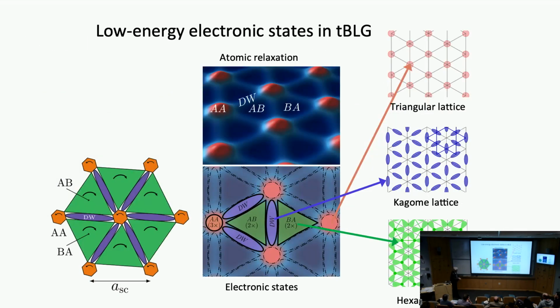And if you analyze this relaxation pattern that I showed you, it consists of three different lattices. These little sites here, the AA sites, form a triangular lattice. That's the triangular lattice. The domain walls form a Kagome lattice, and the AB/BA triangles form a hexagonal lattice or a honeycomb lattice. So all three lattices together, and that's a mess.